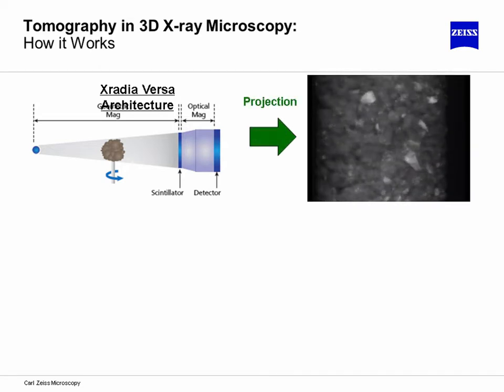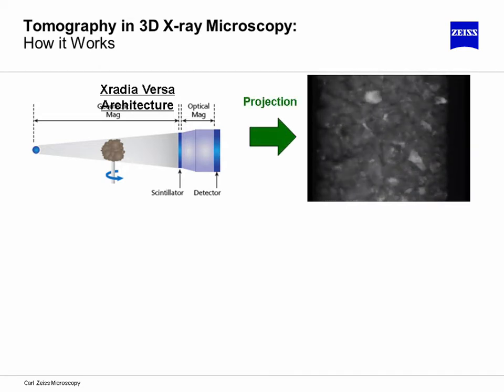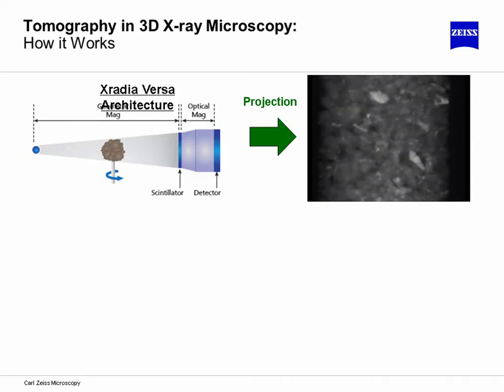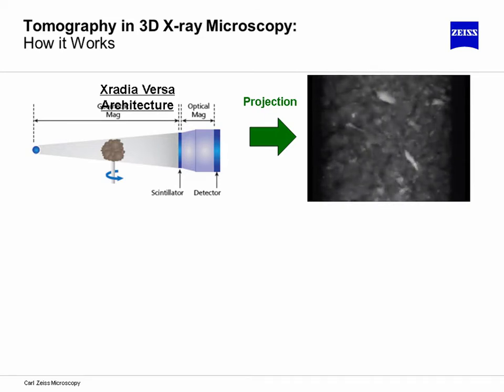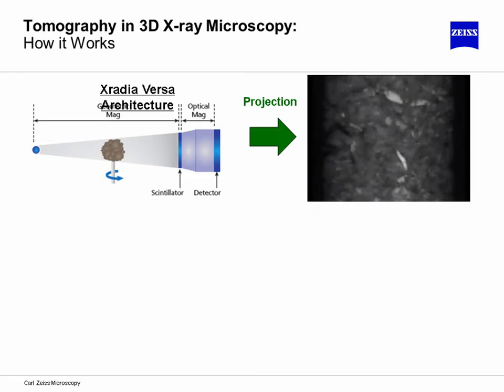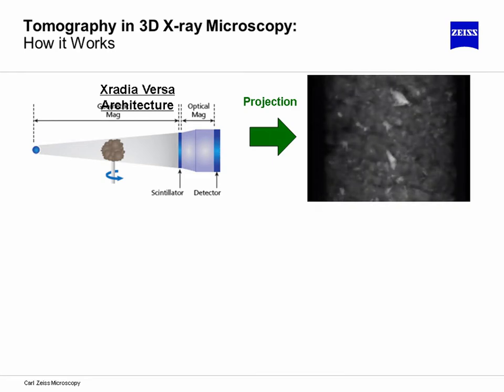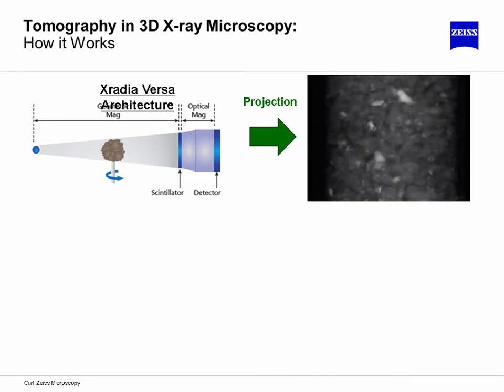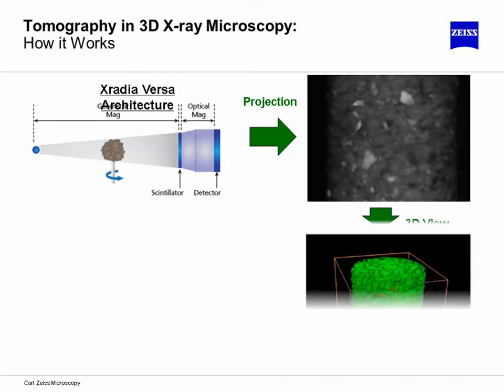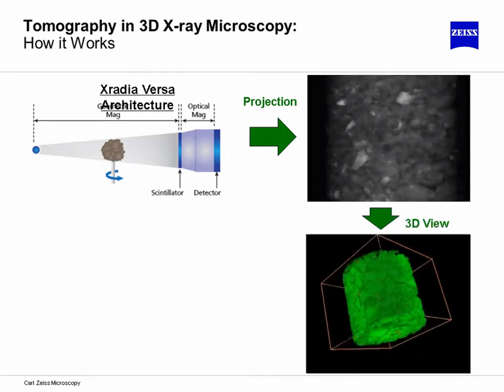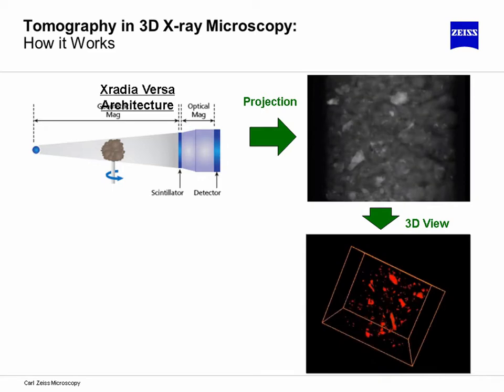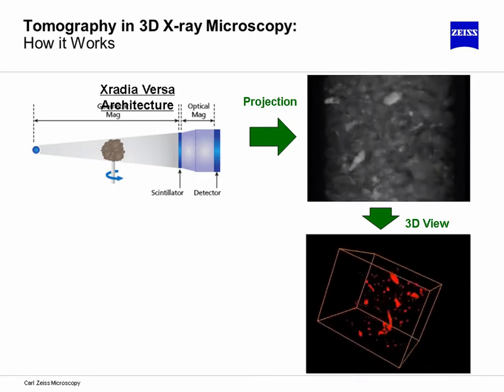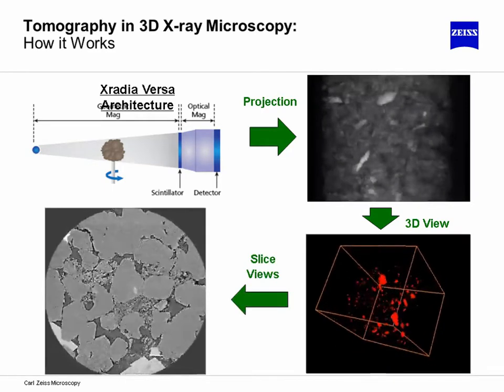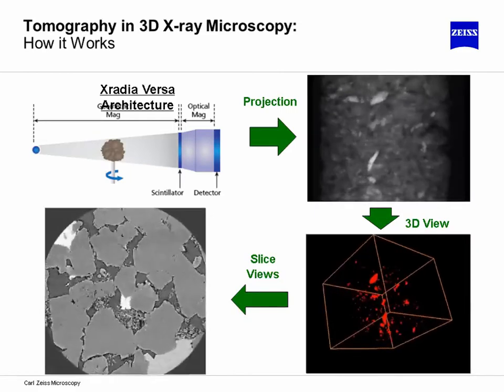And as you rotate the specimen at multiple increments, it can be up to several thousand different projections, or as few as a few hundred, really depending on the resolution requirements. You obtain these radiographs that are then collected, and these are then processed, corrected, and reconstructed into a virtual 3D volume that can then be further quantified.